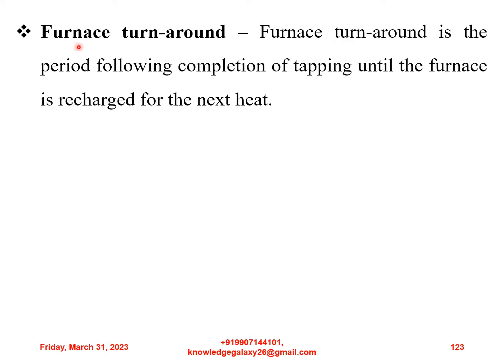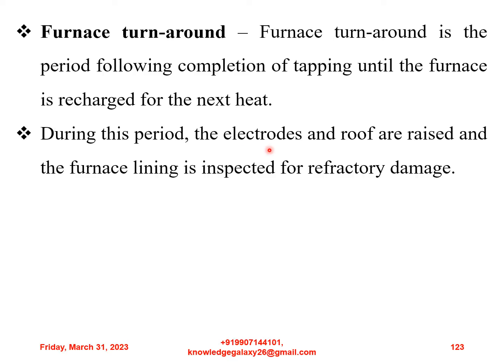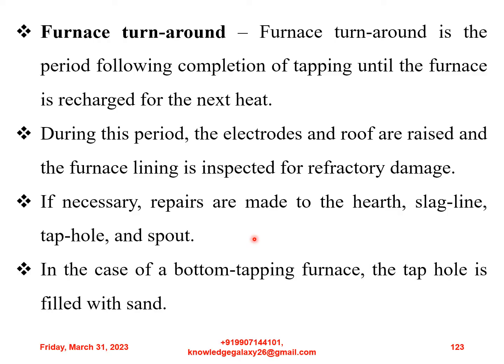Next, last but not the least of the steps is furnace turnaround. Furnace turnaround is the period following completion of tapping until the furnace is recharged for the next heat. During this period, the electrodes and roof are raised and the furnace lining is inspected for refractory damage. If necessary, repairs are made to the hearth, slag line, tap hole and spout. In the case of a bottom tapping furnace, the tap hole is filled with sand.